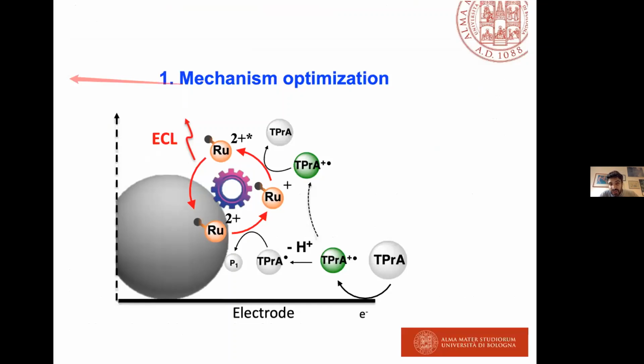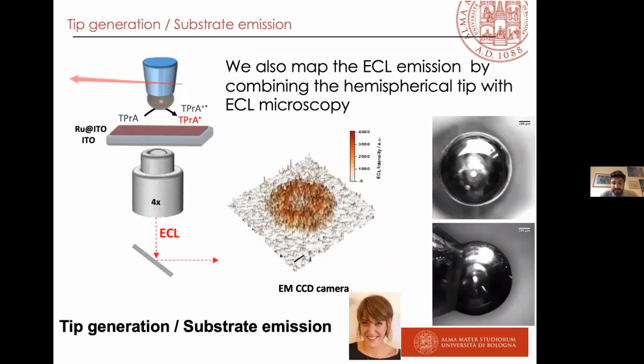Basically, I divided the presentation in 3 parts. The first one is on the mechanistic optimization. So we start from the Bard paper, the 2002 paper, and we did again the same experiment, different tip substrate. In fact, we call it tip generation, substrate emission, inspired by the SECM, scanning electrochemical microscopy, world, but this is another story. So we did the same experiment, moving the tip closer to the ruthenium layer or far away from the ruthenium layer, but instead of a photomultiplier tube, as Bard did, we used